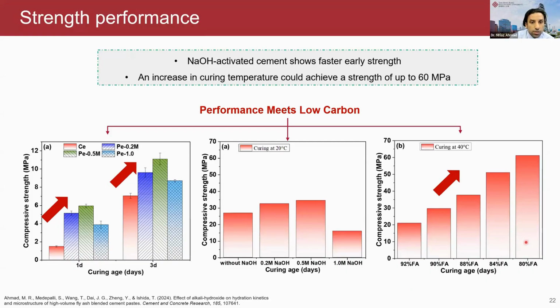And you can see that when we use this 80% fly ash, the compressive strength can reach 60 megapascal, which is a very high strength. It is almost qualified for structural grade concrete. So these results prove that we can achieve both low carbon and high performance concrete, even when we are using a very low amount of clinker.